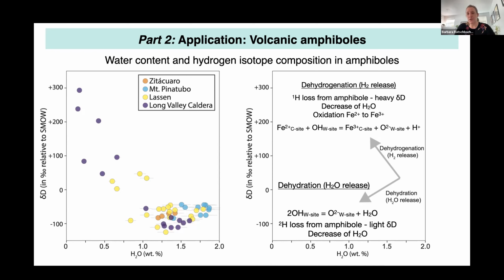So in the formula, you can also see here on the right, dehydrogenation is associated with the oxidation of ferrous to ferric iron. So that's really important for us. We need to figure out whether dehydrogenation has impacted those amphiboles. And then the second process is dehydration, which is the release of water from the structure.